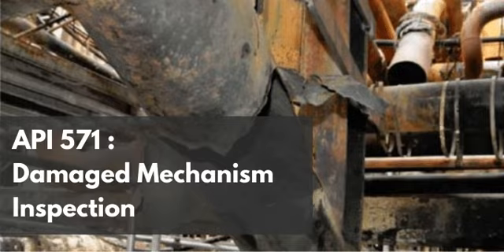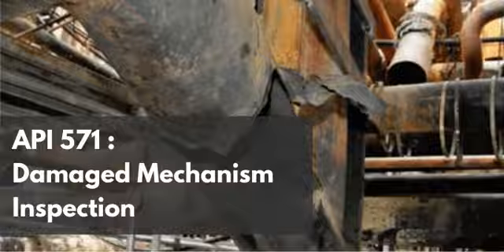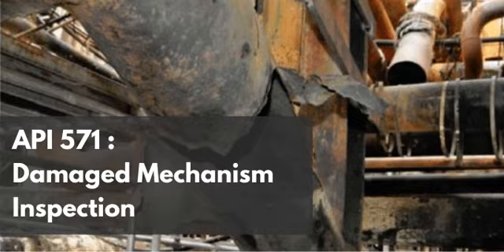You place a transducer on the outside of the pipe. It sends high-frequency sound waves into the steel at an angle, say, 45 or 60 degrees. Those sound waves bounce around inside the steel. If they hit a flat, smooth surface, they bounce away.